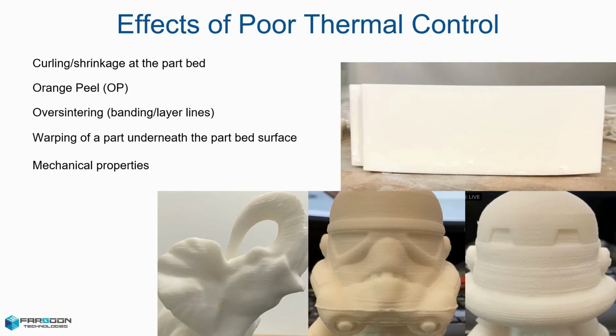So there's a couple of things that we can look out for either in process or when the build is sintering or after the build is complete to identify if we have poor thermal control. The first being curling at the surface of the part bed, usually seen as corners or sides of a sintered layer peeking through a freshly laid layer of material. This is due to insufficient energy at the part bed. If curling is seen throughout the part bed, raising the part heater temperature is advised. If curling is seen in specific areas, for example, the front right corner or back left corner, then raising the corresponding heater ratios is advised.